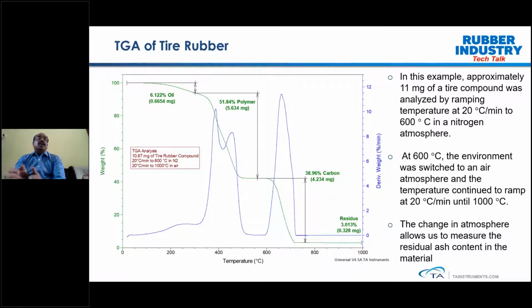As we heat further, we see the polymer decomposition, which accounts for almost 51.84%. At this point, the weight is again stabilizing. Once the temperature reaches 600 degrees, that's when we do a gas switching. We switch from nitrogen to air, which burns off the carbon black present in the polymer compound, and immediately we see the weight change corresponding to the carbon black decomposition, which accounts for 38.96% in this particular case.